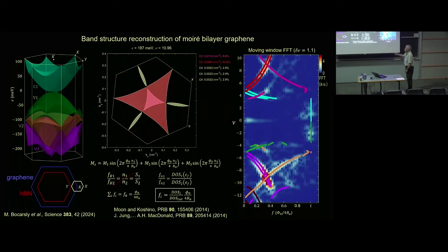Namely, we can reconstruct the band structure quite accurately from these quantum oscillations. And the main finding is that the lattice relaxation is significantly larger than what is usually assumed in the literature. These parameters are usually taken to be of the order of 1. And this larger relaxation gives rise to more overlapping mini bands and to smaller band gaps.